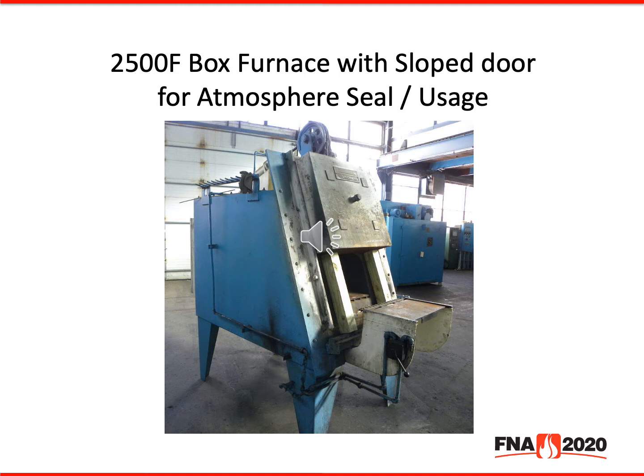In the recent past, these furnaces seem to have been supplanted by vacuum furnaces because vacuum can provide the higher temperature application. Most of these furnaces were used for air quenching, so the vacuum furnaces nowadays have at least a 2-bar and all the way up to 10-bar to provide the higher pressure quench, and the furnaces don't have to be idled; they can be shut off and turned on when needed. So these have fallen out of favor towards the vacuum furnace market, but are still a vital piece of equipment over the years.